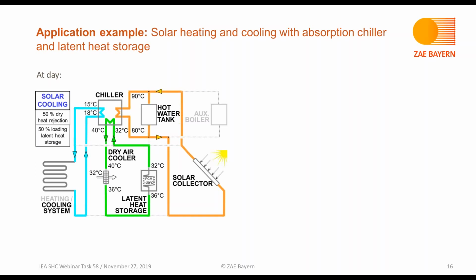At day, the system is driven by a solar thermal collector, providing heat at 90 degrees C to a thermally driven absorption chiller, which in turn provides cold at 15 degrees C to a cooling system. And to keep this process running, heat needs to be rejected. So this is now the green circle. Heat needs to be rejected at 40 degrees C. And in this case, this is done partly by a dry recooler and partly by storing the heat in the latent heat storage. Storing here means melting the PCM.